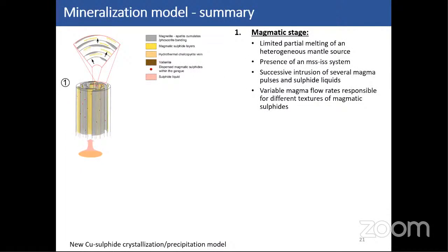So concerning the updated model now, as suggested in the provisional model during the middle of this presentation, we have three stages. First of all, the magmatic one, which consists in the limited partial melting of an isotopically and chemically heterogeneous mantle source for the base metal budget, which is followed by the ascent of a sulfide liquid, which separates into a monosulfide solid solution, which remains at depth, and further ascent of a copper-rich sulfide liquid, which further differentiates into bornite and chalcopyrite during the ascent, and which forms different textures, which are disseminated grains, elongated assemblages, and sulfide cumulates, depending on the magma flow.